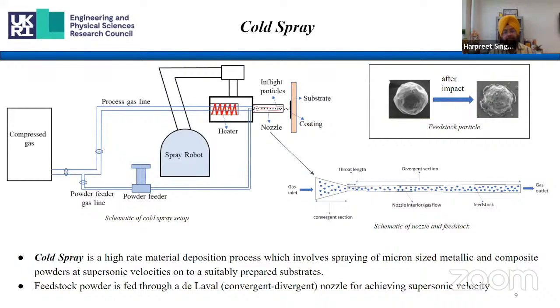We have the capabilities of up to 1000 degrees Celsius as well. But the major reason of heating here is not to heat the particles, but to heat the gas, actually. And of course, some heat is picked up by the particles, but that is not the prime objective of this. Of course, this facilitates to some extent. They soften some particles, but majorly it goes for these thermodynamic reasons here. Again, a lot of studies, a lot of simulation guys have worked on designing these nozzles and so on, if you see the literature.